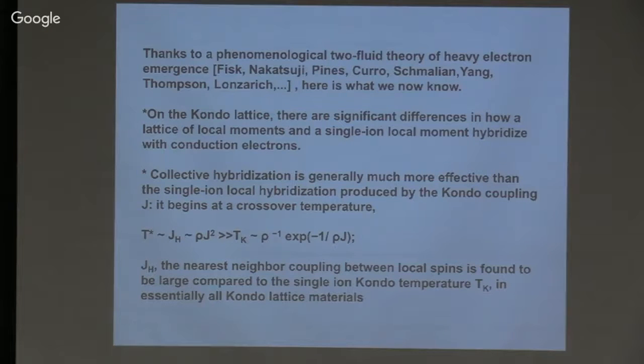So everything is determined by T star, and it's quite large when you do the experiments carefully. It turns out to be really large compared to a typical Kondo temperature. So you can sort of forget about single ion effects. You think a little more and say, oh, that means the hybridization has to be collective.